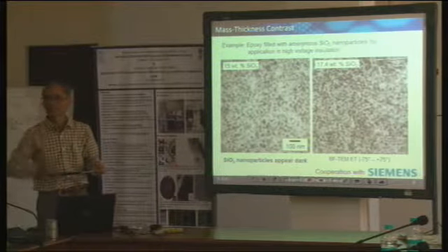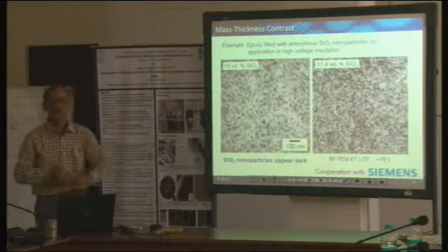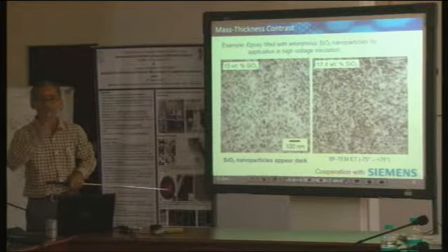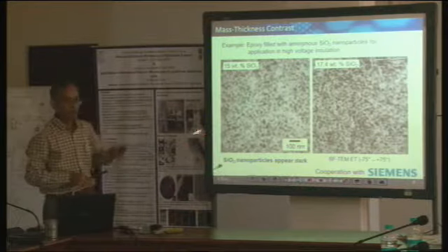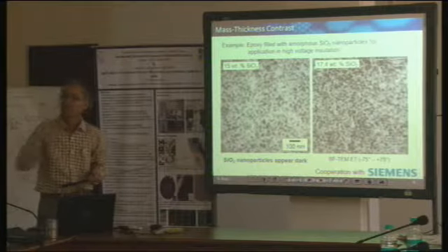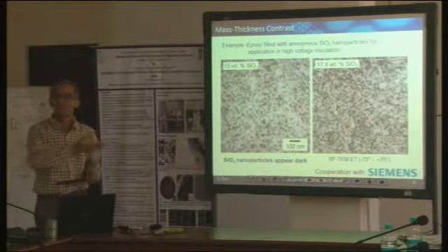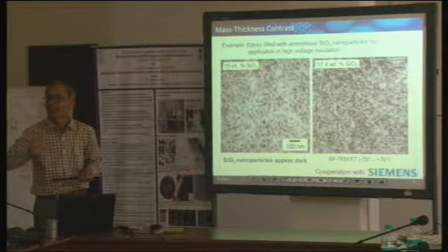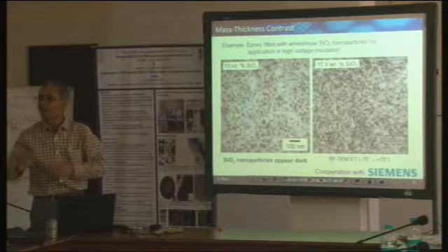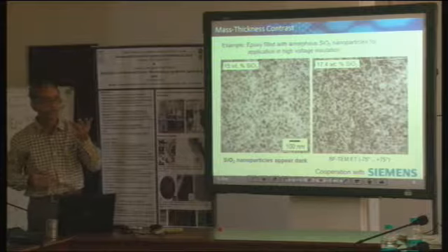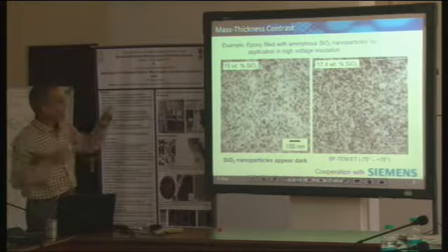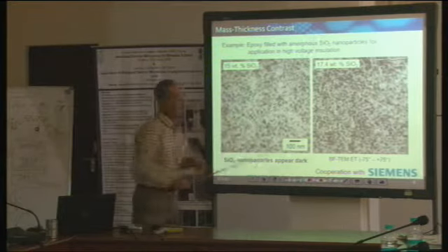No, it would not have been the same, because we are going to talk of one more contrast mechanism, and that's what is the Bragg diffraction contrast. But we will come to that maybe later. Right now, however, it doesn't play a role because it's an amorphous material. There is no scope for diffraction contrast here. There is no question of whether my lattice planes are favorably oriented for diffraction or not. That question doesn't come into play at all, and that's why